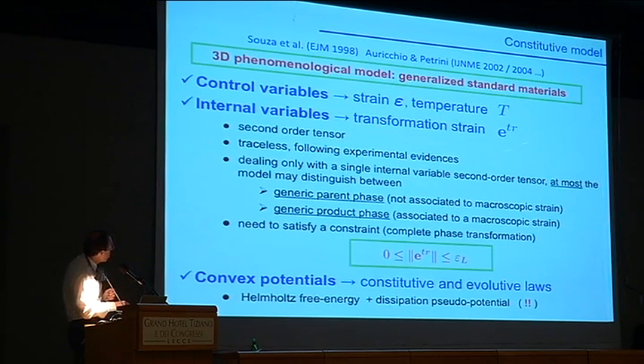And in fact, if you choose only this quantity as internal variable in your model, you cannot get a huge description of what's going on inside the material, and you can only try to describe what I name a generic parent phase from a generic product phase. So you don't get a very good description, but we believe it's already enough for many applications. The generic parent phase is basically all the phases which are not associated with macroscopic strain, while the generic product phase are all the phases which are associated with macroscopic strain. So we don't make any deep distinction about what's going on inside the material, but we just distinguish between these two quantities.